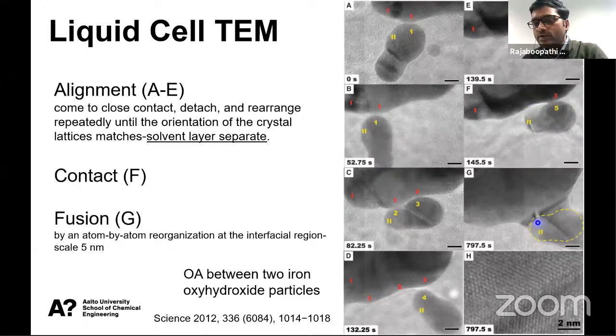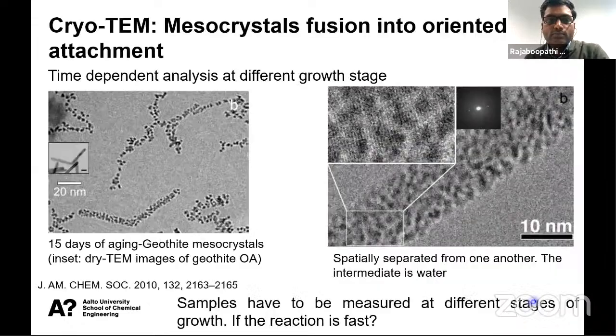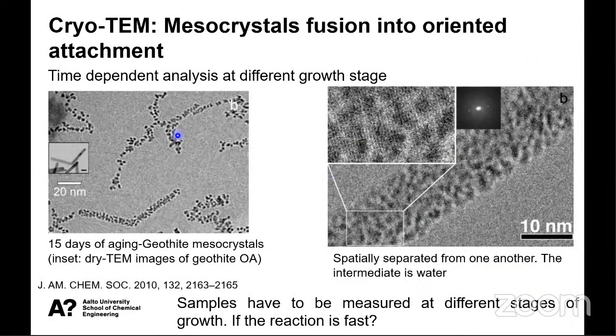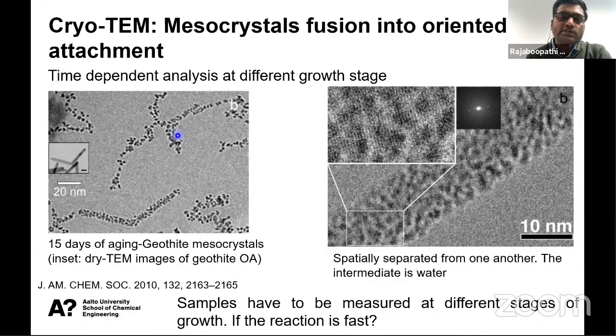Then it attached completely. So the whole process happens within 15 minutes. Within 15 minutes, the attachment process is completed. And this is the lattice fringe image of this attachment, where there is no lattice mismatch in the process. And they have used a cryogenic TEM to see whether it is mesocrystals or oriented attachment.